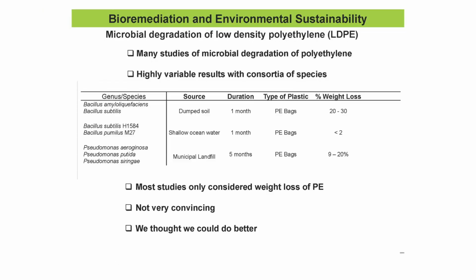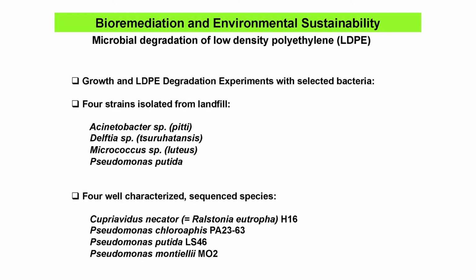We don't know why. So there are many studies of microbial degradation on polyethylene, but the results are very, very highly variable in the literature. In some cases, it takes months for different kinds of bags, and the weight loss, measured by weight loss only, maybe 20 to 30% or 2%, 9 to 20%. So very, very variable, not very convincing. So we thought we could do better.